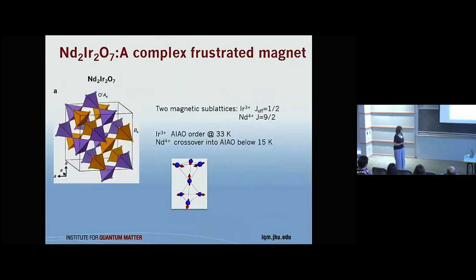But it ended up being a very interesting and very challenging frustrated magnet, because in contrast to all other iridates, we have not only magnetic ordering in the iridium sublattice, but also a neodymium sublattice, which is magnetic and which eventually, as people saw, orders. So we have two interpenetrating frustrated sublattices of tetrahedra. Iridium has effective moment 1/2, and neodymium has a very large effective moment 9/2. Iridium has extended orbitals, and all the electronic structure around the Fermi surface is formed by iridium orbitals, while neodymium is 4f, with very localized orbitals.